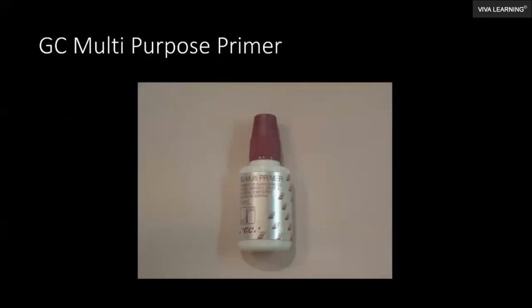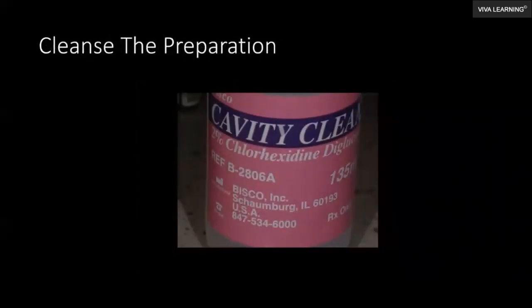Again, the advantage of this is one primer for lithium disilicate as well as zirconia. I don't need two different primers, and this is going to enhance bond strength. This will allow the cement to bond better to the intaglio surface of the material. So we've primed the internal surface of our veneer. Now I have to make sure that my cavity or my crown prep or my veneer prep is totally disinfected or clean.